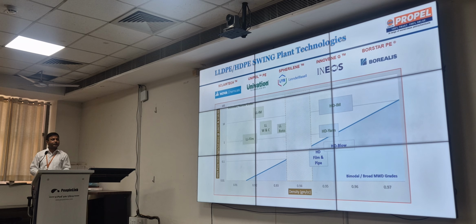So different technologies with different grades, ranging from MFI to density, for different applications. Univation gives unimodal grades for the LL film applications. With Nova Chem or Univation, you can get this range of MFI and density with these products. And Spherilene comes just in between, 0.92 to 0.94, and INEOS and Borealis come to the right side, for applications like SD injection molding, SDR, SD blow and bimodal grades. So these are the technologies preferred for such applications. Not every technology can produce grades which suit all your applications. Different technologies have different positives for different applications.